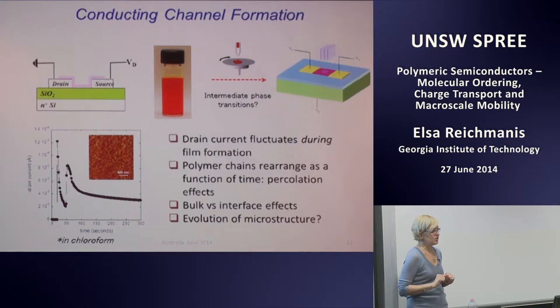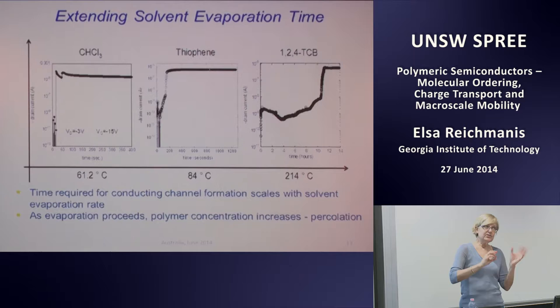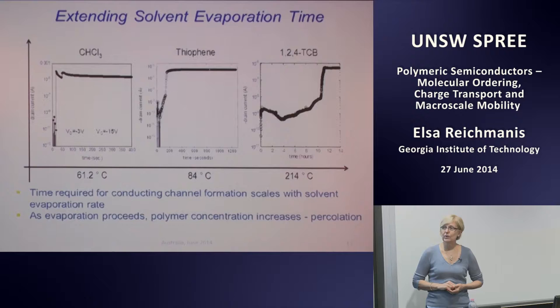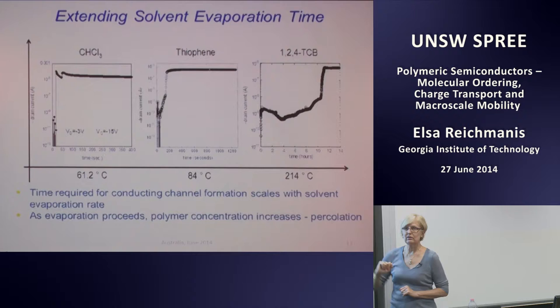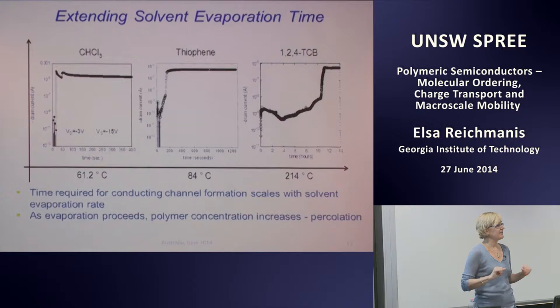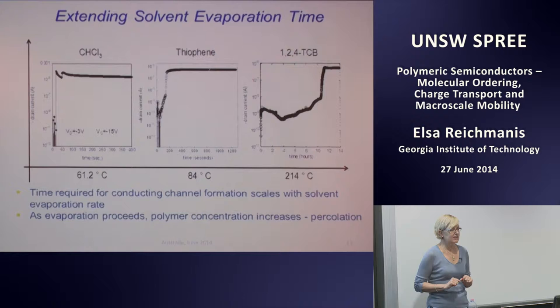If we look at using chloroform as a solvent, it's a low boiling point solvent, it evaporates really quickly, so there's very little that we can do to actually interrogate that droplet as the solvent evaporates. So we started looking at higher boiling point solvents. If we look at chloroform, thiophene, and trichlorobenzene, the time required to form a thin film is extended relative to the boiling point of the solvent. We typically get a percolation network from all of these systems.